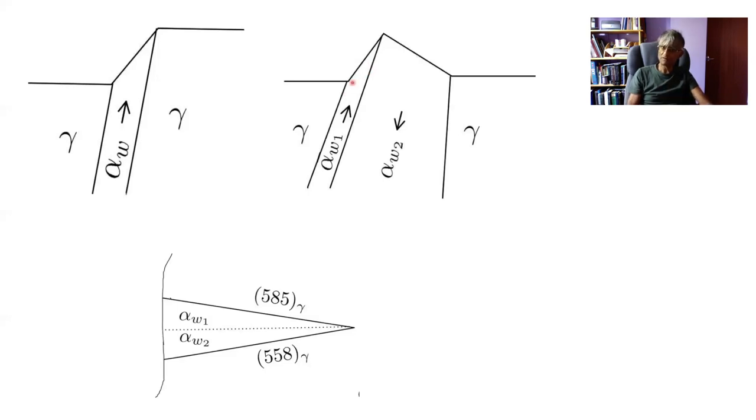So when we look at the surface relief and the deflection of the scratches, we actually see tent-shaped surface relief rather than just a single tilt like this. And if you recall from the crystallographic theory of martensite, the habit plane, the shape deformation and the orientation relationships are mathematically connected. So if I have this plate causing a displacement in this direction and this plate in a somewhat different direction, not exactly parallel, then the habit planes must also be different. Like so. The habit plane is irrational, but let's say it's close to 585 austenite. So these two plates have different habit planes, and as a consequence they form a thin wedge instead of a lens-like plate. Really quite clever.